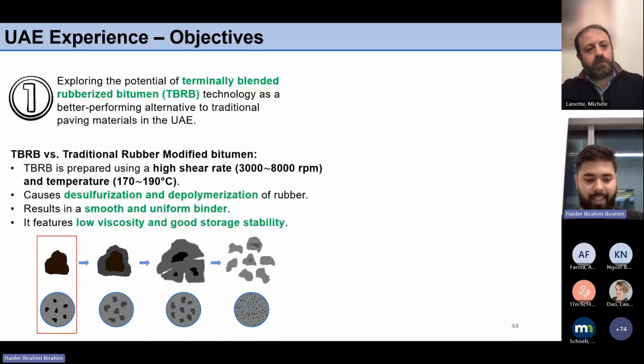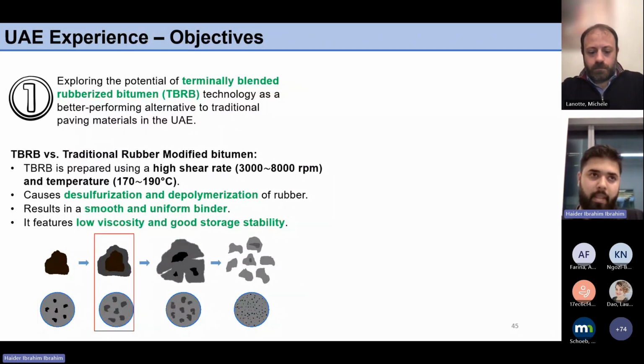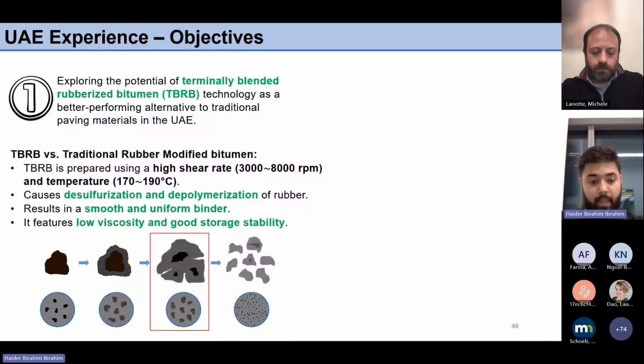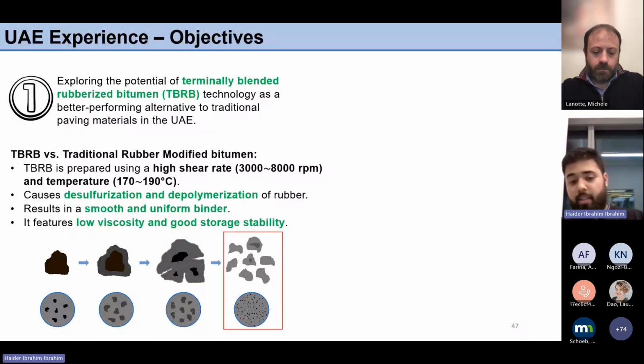If we start on the left, it's just an image of when the crumb rubber is introduced to the bitumen. Once it's settled there, the crumb rubber, because of its diffusive properties, absorbs the light fractions from the bitumen and swells. And with further agitation, it depolymerizes and the long chains are broken. And then finally, we get a crumb rubber modified bitumen with completely disintegrated rubber inside of it. And this is what we call the terminal blend.